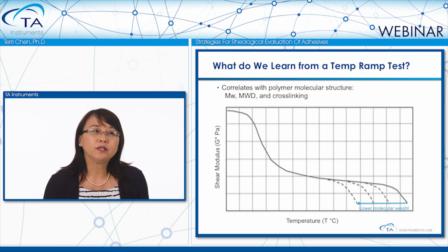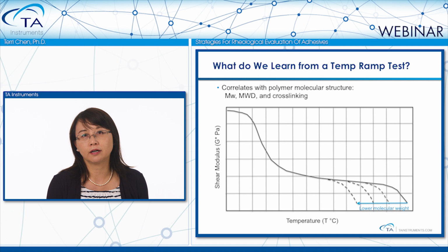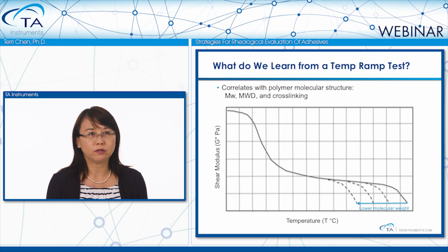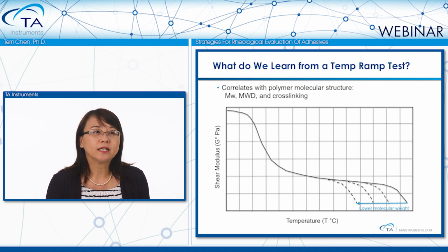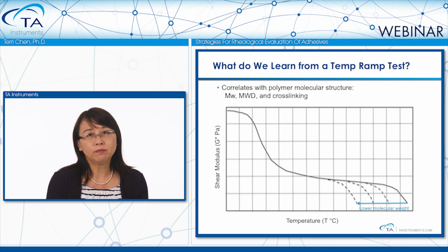The dynamic temperature ramp experiment on adhesive-based polymers can also be used to compare polymer molecular architectures, such as molecular weight, distribution, and cross-linking. For example, when testing the same type of adhesive polymers with different molecular weights, one will observe that if the polymer has a lower molecular weight, it will show a shorter rubbery plateau region in a temperature ramp experiment.